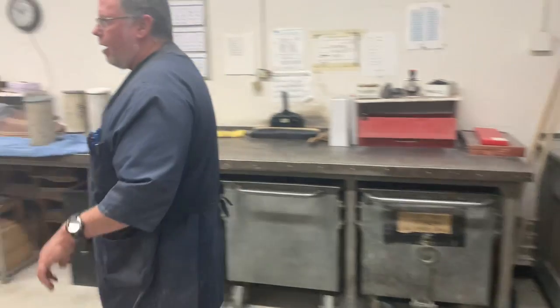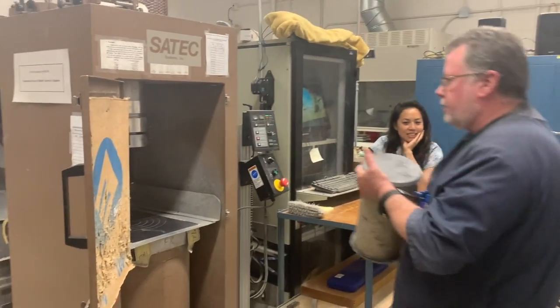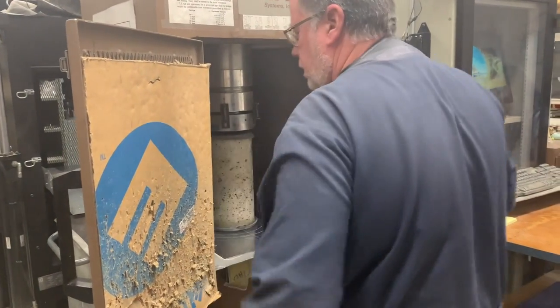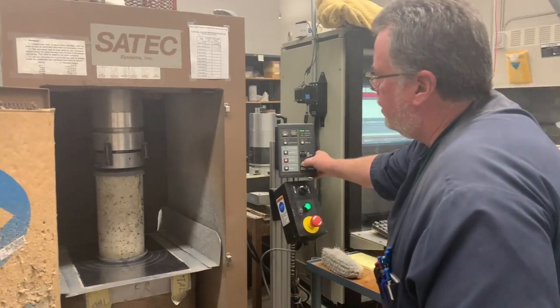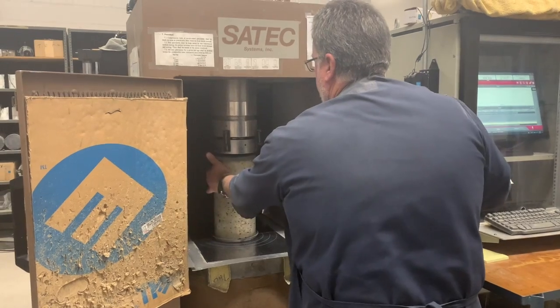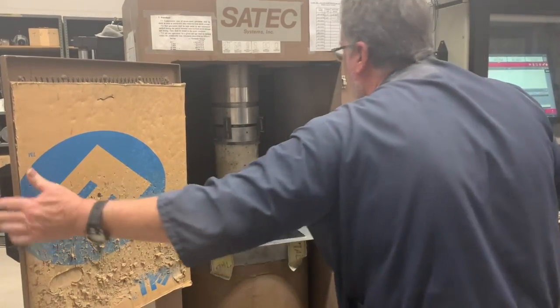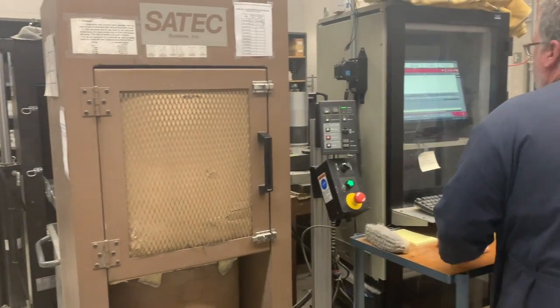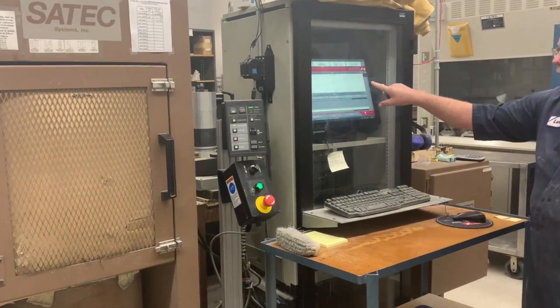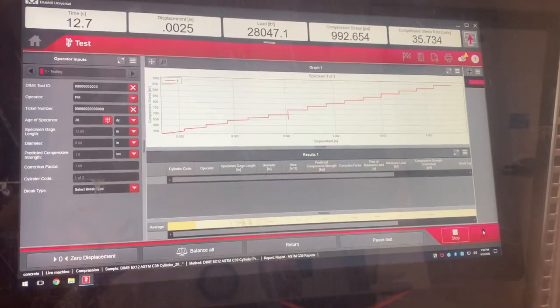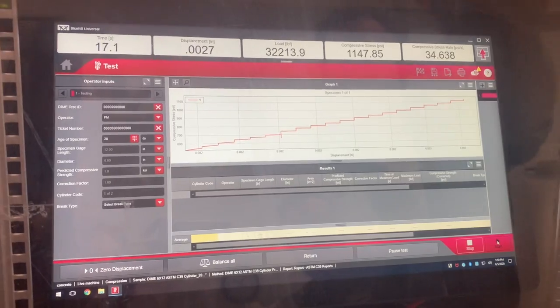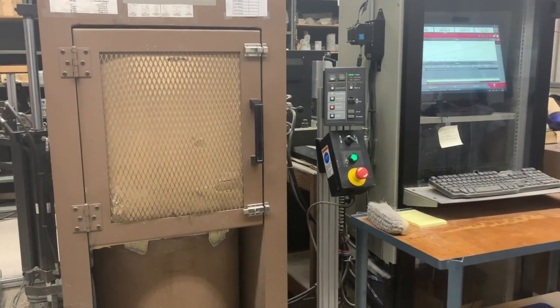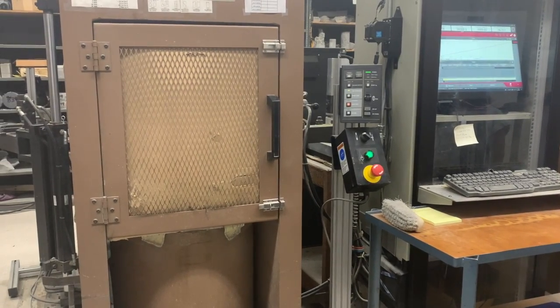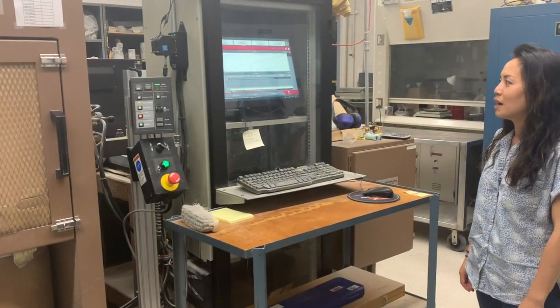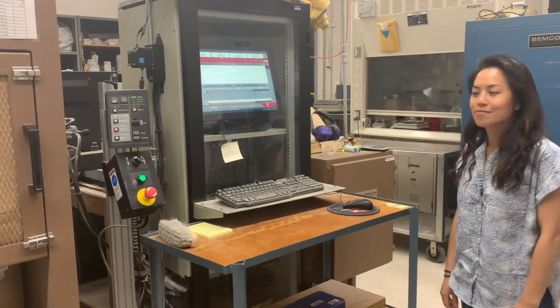So after time of curing for the capping compound, then we actually will break the cylinders. The cylinders are loaded into the press. So we'll load and center the cylinder into the press. If you want to look at the graph here, we're charting the graph, the strength gain, and what we'll get is a total load in pounds, and then is converted to PSI. 6-inch cylinders doing compressive strength is daily work. Every single district will have this type of test setup, more or less, to verify good quality assurance on concrete placements.